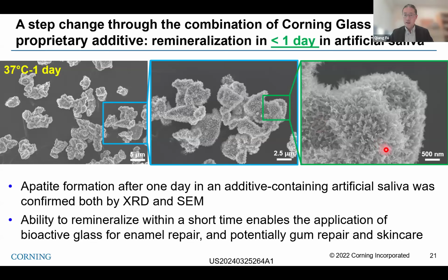You can see this at a higher magnification. So we believe this ability to form apatite shows how effective this material is. If you think about 45S5, it takes over 2 months even to form any apatite. Now in our material, we can form it within 1 day. We really see a step change in performance in bioactivity. So that is the second example I want to show you.